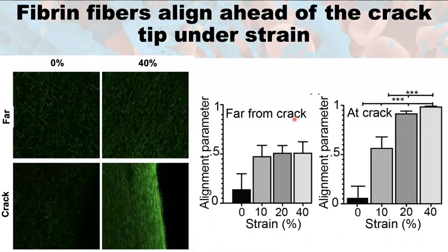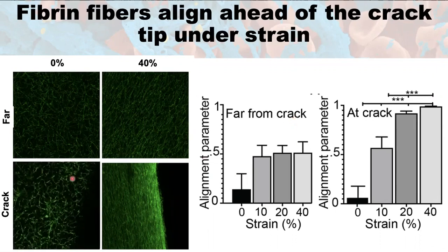So we wanted to look at some of the structural changes that are happening in the clot to get a little bit of a better understanding of what is driving this rupture process. So to do this, we took confocal microscopy images of areas in the region immediately ahead of the crack tip and those that were further removed from the crack tip. So here you can see the images that were removed at 0% strain and 40% strain. And then here you can see images that are immediately ahead of the crack tip.